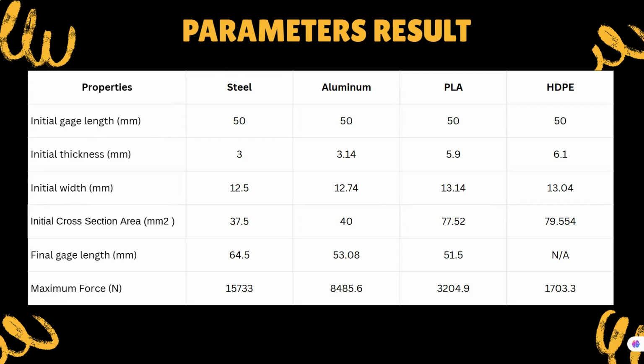So this is the result for the measurement before and after. The initial gauge length, the middle part that we measured, are all the same at 50, but the ones we need to pay attention to are the initial and the final, where we can see the difference, and each specimen with a different material has a different elongation. And then we can see the material that can receive the biggest force is steel. So from here, we can assume that steel has the highest strength.